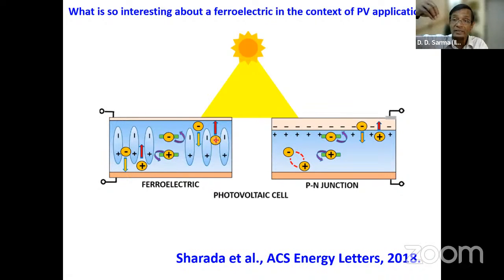So they get separated. Once they get separated, they cannot recombine. And in fact, they then travel through this ferroelectric photovoltaic material, avoiding each other all through, because they have their minimum of energy at different places, at the two ends of the dipole. And so they move, avoiding each other so they don't recombine, so you get higher efficiency. And that's why one is excited about ferroelectrics.